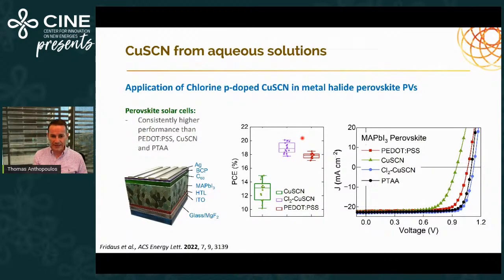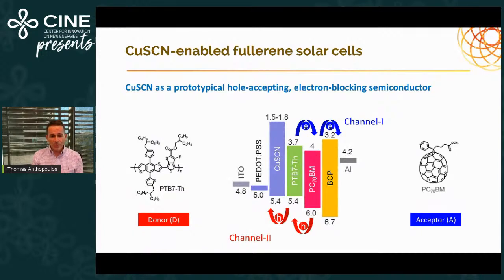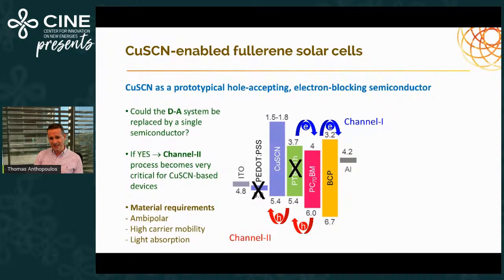So clearly, the ability to have a good hole transport layer makes a difference in our perovskite devices. What we have also been able to do with this copper thiocyanate in the past is to radically rethink how we build devices and use it as a fundamental building block for understanding basic processes. So we took one of the bulk heterojunction devices and we thought, okay, could we eliminate the PSS and the actual donor polymer, and instead use copper thiocyanate together with an acceptor material like a C70 PCBM, and see whether we can make a single photoactive material solar cell.